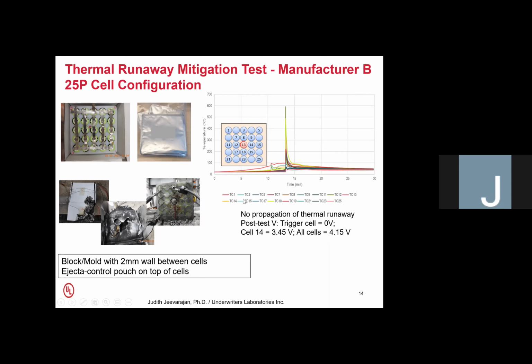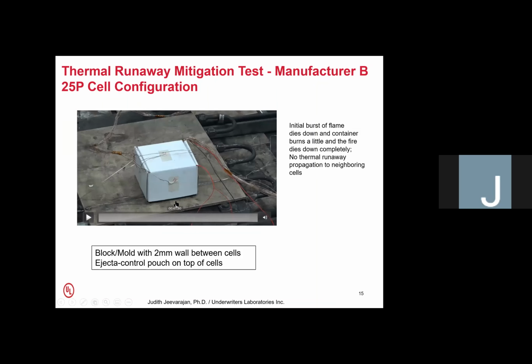And what we observed in this case is that there was only one cell that had a slight drop in voltage, but all the other cells were at the full state of charge, and even the one that had the slight drop in voltage really did not have a thermal runaway. It was probably a self-discharge due to warmer temperatures. A quick video here also.